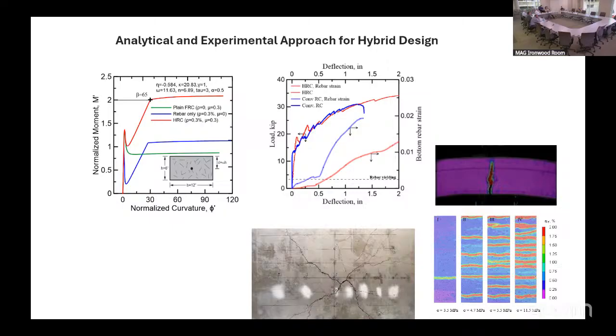is basically what the fiber concrete is doing by itself. The blue line is when you design it as reinforced concrete. In other words, it cracks, but it takes time for the rebar to actually start carrying the load. That gap before the rebar is carrying the load is picked up by the fiber. So if you combine the fiber with the rebar, you would all of a sudden more than double up. So the idea is that if you're doing reinforced concrete, putting fibers in is going to double up your strength, because now your response is going to be pushed to a much higher level.